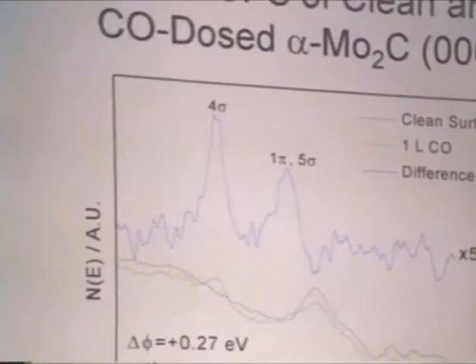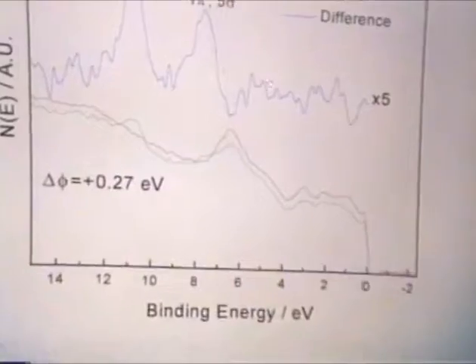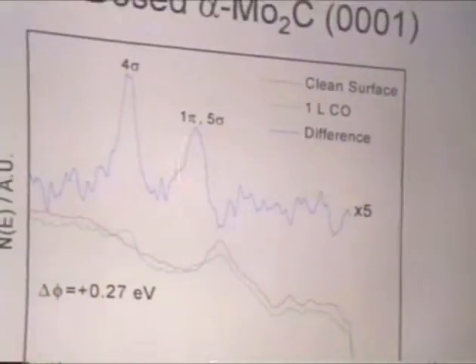on a clean surface, as indicated by the red data. And then we took a UPS spectrum of a dosed surface that had 1 Langmuir of CO on it and took a difference spectrum. And you see that we see 2 peaks out of the background. These 2 peaks look very much like a classic example of CO chemisorption on metals. The interpretation is as follows. The splitting between this peak and this peak is equivalent to the splitting in a gas phase UPS spectrum of CO. This indicates that we have gas phase-like, molecularly adsorbed CO on the surface.